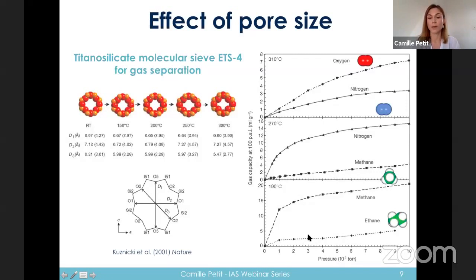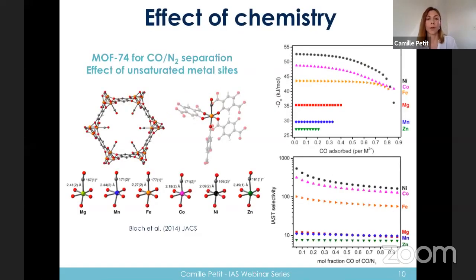And so you see here that we can separate ethane from methane, or methane from nitrogen, and nitrogen from oxygen, even though the difference between the size of those different molecules is relatively small. So it's a nice example of a molecular sieving separation process. If we look at the effect of chemistry, I take here the example of a MOF, which is called MOF 74.